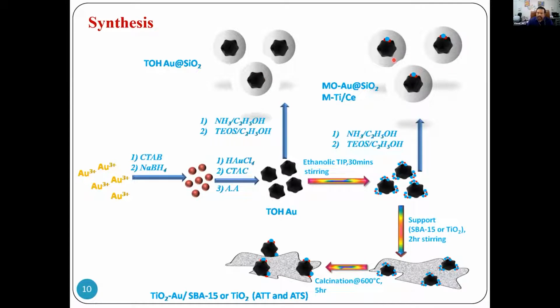You can also make what is called an inverse model catalyst, where this gold nanoparticle can be supported on a little bit of titanium where this encapsulation happens. So there is a nice interface that is formed between gold and TiO2, and there is an encapsulation of porous silica on top of that. This creates an active metal interface between the gold nanoparticle and titanium.